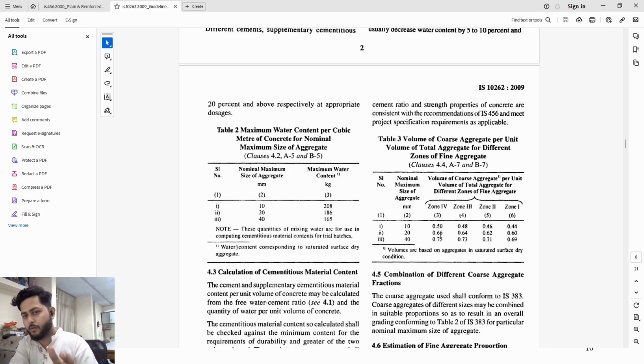Now, once you know the coarse aggregate to the total aggregate ratio, you have to conserve the volume. By volume conservation, I mean that you have to calculate the total weight proportions of each of the constituents in your concrete mix for 1 meter cube volume of concrete. You already calculated the water content, you already know the cement content, and you know the specific gravities of all the materials: the cement, the fine aggregate, the coarse aggregate, water, and if you're using any chemical admixtures, you need to know the specific gravity of those too. Once you know the specific gravities of all of them, you can calculate the volume of aggregates by conserving the volume to 1 meter cube.